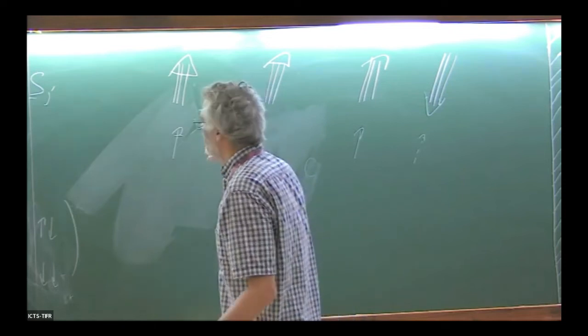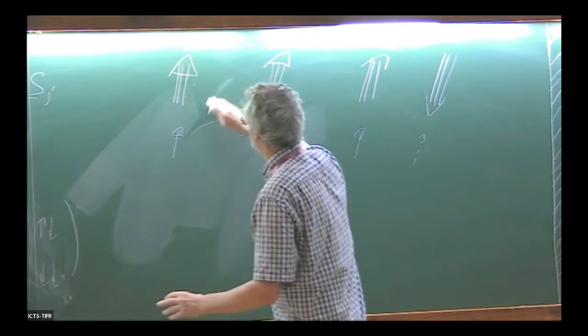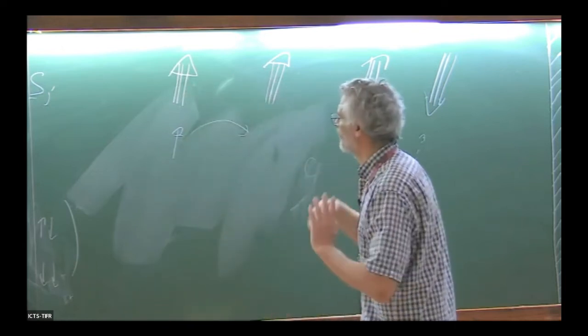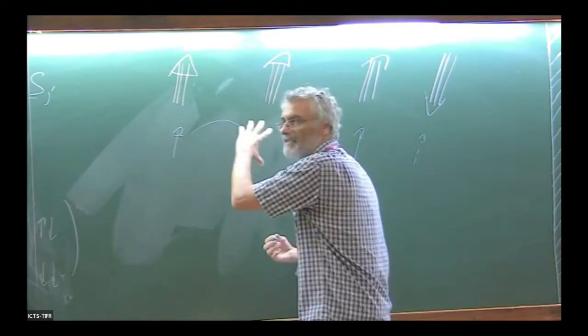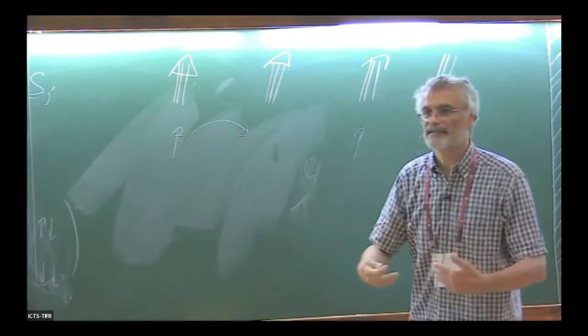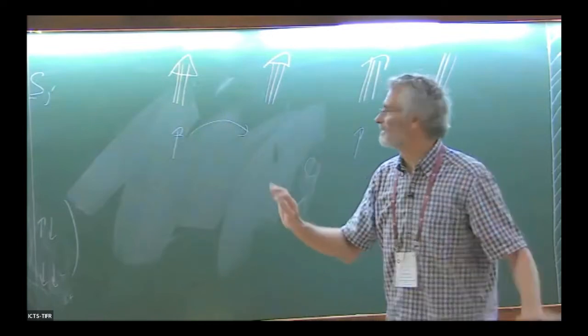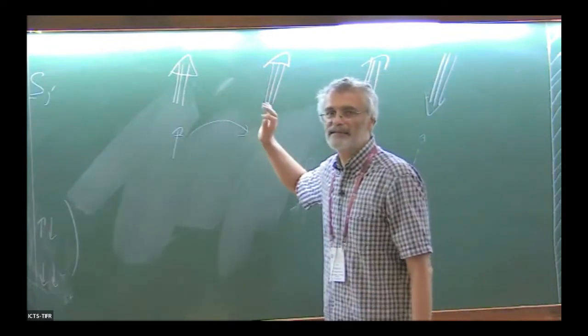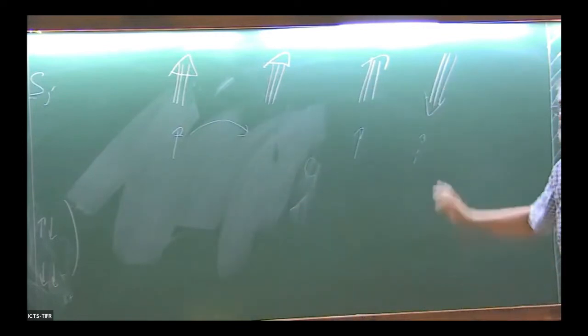And we can also turn the picture a little bit different. We can say somehow differently that if there is a sufficient number of itinerant electrons, and this J is not sufficiently large, in that case, the itineracy of the electrons will make the local spins ferromagnetically aligned. So this is an itinerant-electron-driven ferromagnet here. And in this case, it is not going to happen.